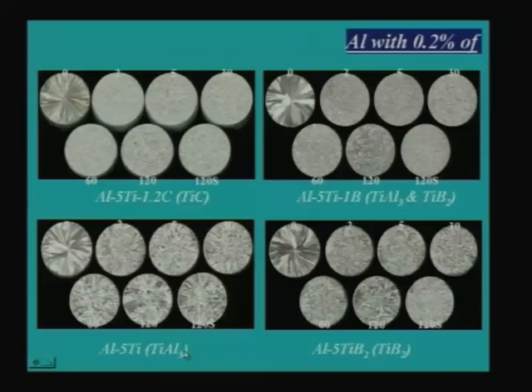Okay, you must have read about heterogeneous nucleation. In heterogeneous nucleation, the interfacial energies are going to decide the wettability of the particle with the aluminum, and that is what is going to decide the contact angle. The lower the contact angle, the better the wettability we say. So that is what one can indirectly get here: TiAl3 is not very good, TiB2 also not very good, and a combination of these two also does not give you as good as what you get with TiC.